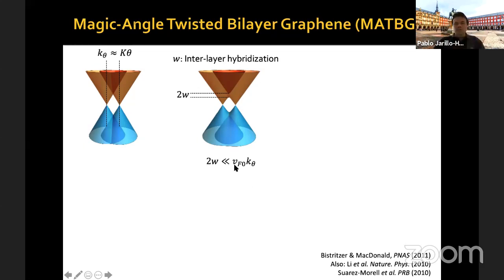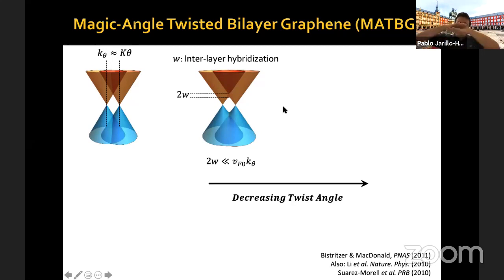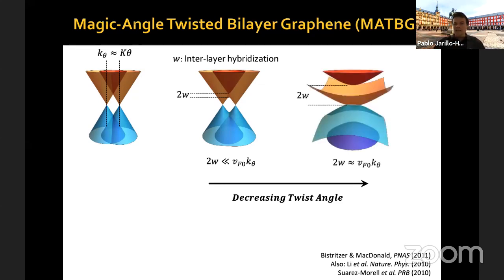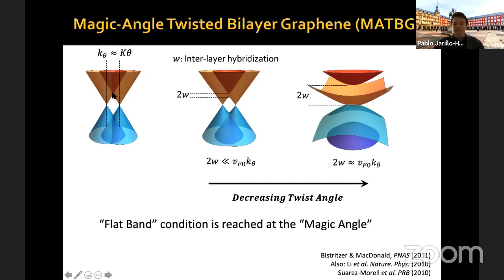Now, this is the situation that occurs when the angle of rotation is such that this interlayer hybridization is still small compared to the original energy at which this crossing point occurs. What happens then is that as you decrease the twist angle towards smaller and smaller angles, the energy of this crossing point gets lower and lower. Therefore, when interlayer hybridization occurs, this lower band gets pushed down lower and lower, and at some point you reach a condition where the interlayer hybridization is of the same order as the energy of the crossing point, and that leads to something known as a flat band condition.